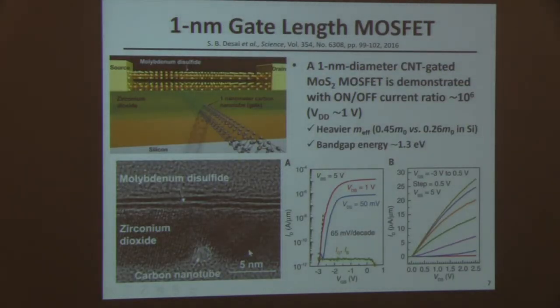But I wanted to point out that a team of researchers led by Professor Javey at UC Berkeley recently published a result where they showed a 1 nanometer gate length transistor, where the 1 nanometer was just the diameter of the carbon nanotube that was used as an electrode for this transistor. And the channel is a 2-dimensional layer of transition metal dichalcogenide, molybdenum disulfide, an advanced 2-dimensional structure. It has no dangling bonds and is very thin, less than 1 nanometer thick. So they showed that if you can make the channel super thin, thinner than the gate length, then you can get a transistor reasonably switching on and off, even at 1 nanometer.